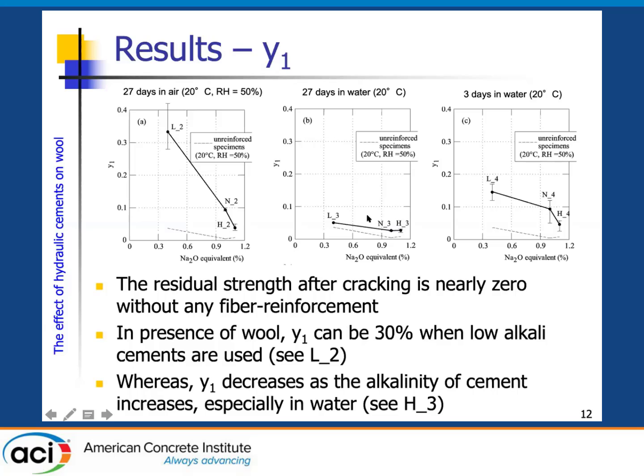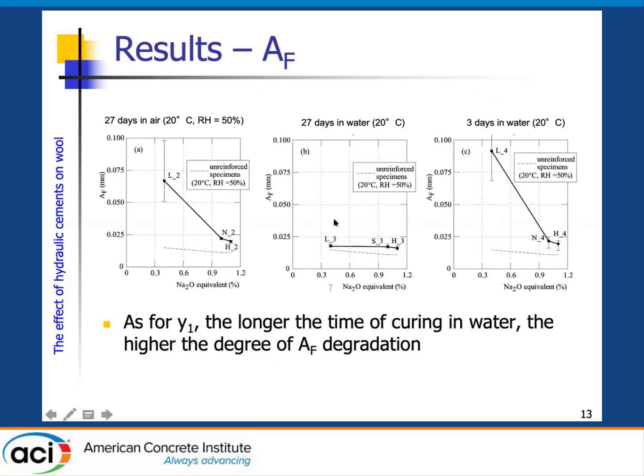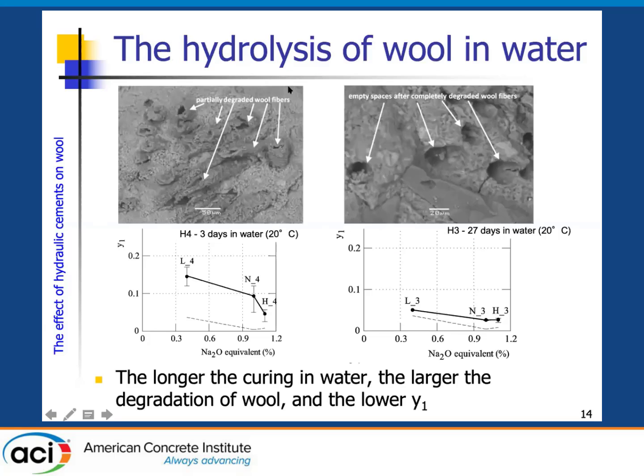related to the maximum content of alkali. Of course, in water, you cannot see any difference among the different cements, because the hydrolysis is accelerated by the presence of water. And the results are similar for AF. So what happens to the hydrolysis? If you see here, after 3 days, only part of the wool is degraded, not all of it. So for the maximum alkali, you have a certain residual strength. But if you leave it 27 days, you can see the wool is completely degraded. So only the hole remains, not the fiber. And as a consequence, you have a reduction of the strength.